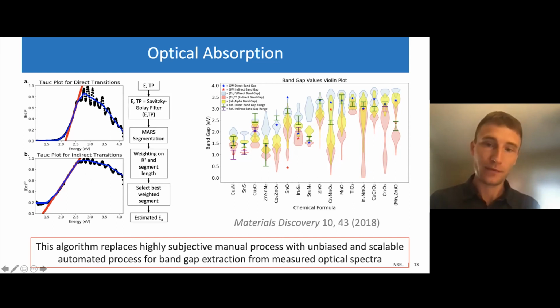So that is reflected by very large distribution of these data. For example, here you could see that the indirect data for this particular material calculated from GW lies below experimental data distribution, and the same thing with the direct band gap. But even the error bars on these GW calculations have smaller magnitude compared to error bars on experimental data that had to do with uncertainty in interpretation of optical absorption spectra, as well as spread of the synthesis conditions that lead to variation of materials properties.